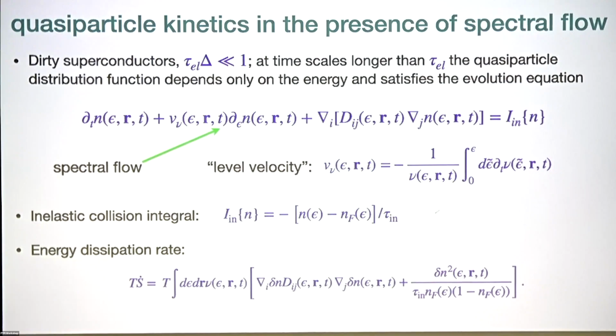And at the same time, because the time reversal symmetry is broken, branch imbalance relaxes quickly by local elastic collisions, and it does not generate these long relaxation times. So the Larkin-Ovchinnikov equations actually reduce to this equation, with one kind of proviso.